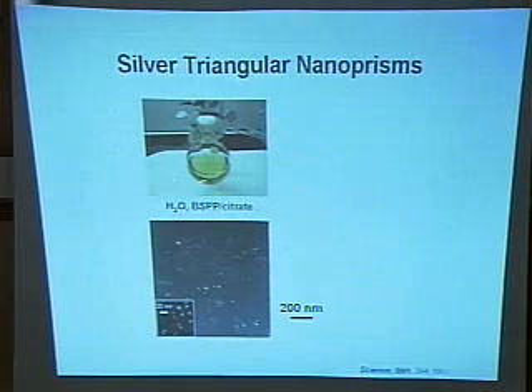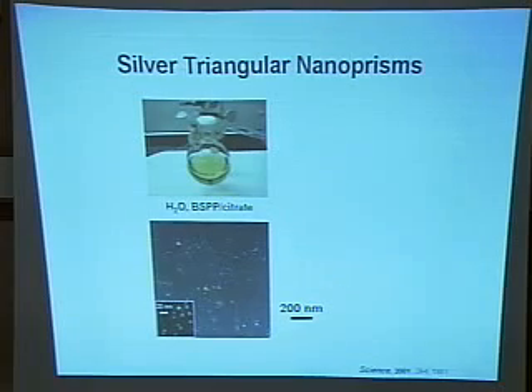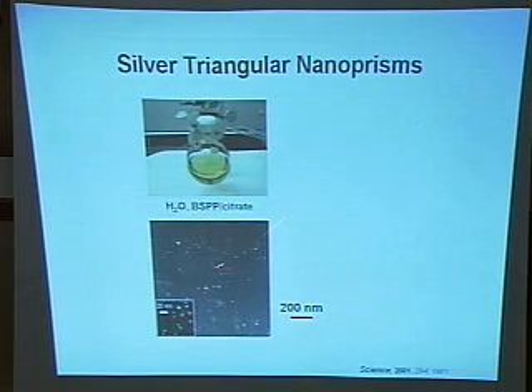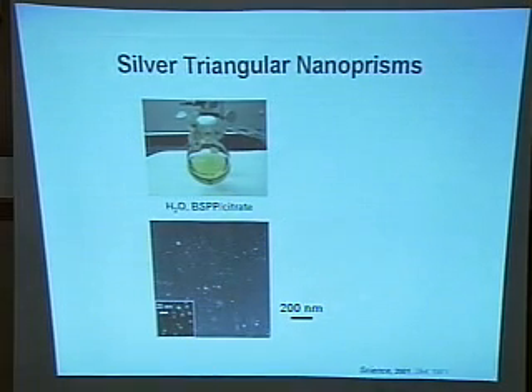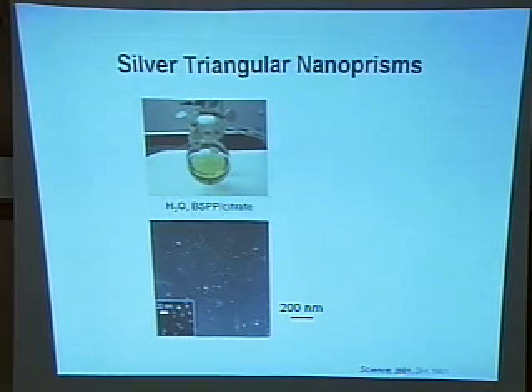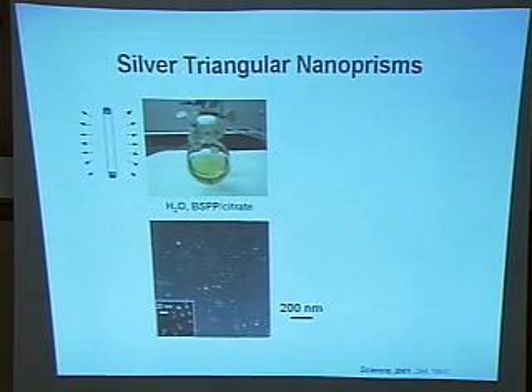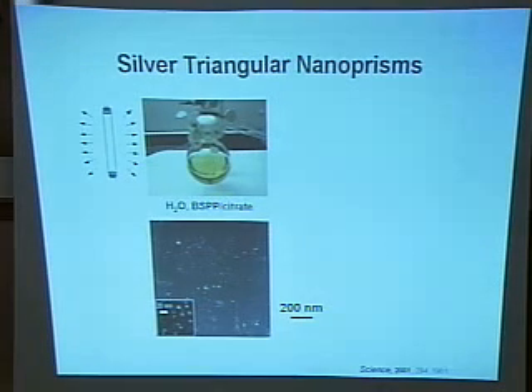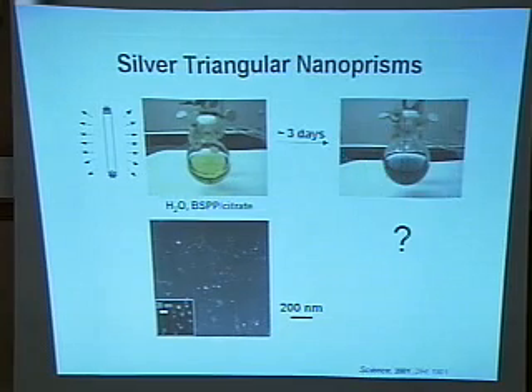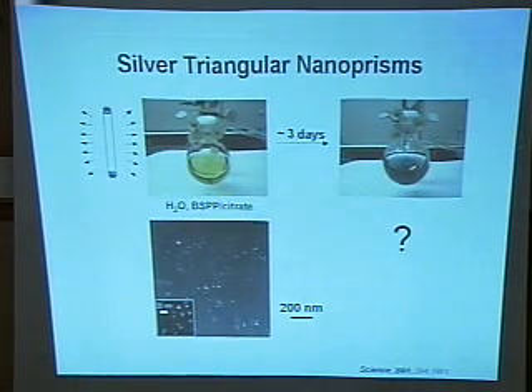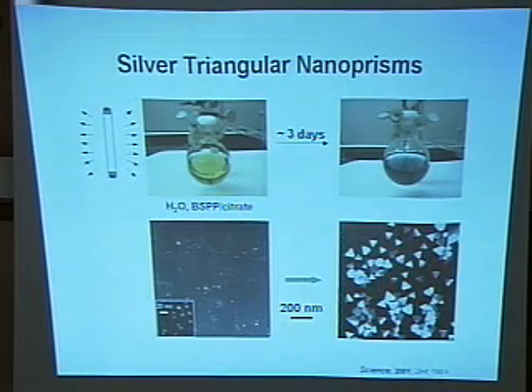So in this flask, it contains a typical silver colloid, with a size from 6 to 8 nanometers. And shining with fluorescent light, it's just regular, like this light. And after 3 days, what happened? Their optical properties gradually change. They absorb, actually they turn blue. And what happened? So we go to the TEM.